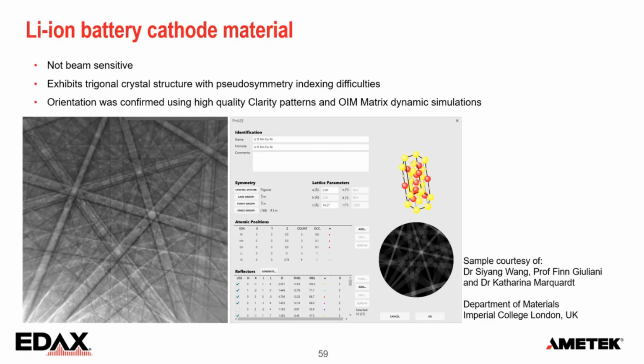So this is nicely polished, and we could get really good diffraction patterns from here. I could use that to optimize my structure file. It's a trigonal material. You see a lot of detail. But the problem that we had during mapping was that in most grains, we had more than one orientation possibility. There's a pseudosymmetry in this trigonal structure. So for this analysis, we were comparing the experimental patterns, just one or two patterns per grain, against dynamic simulations in OIM Matrix.